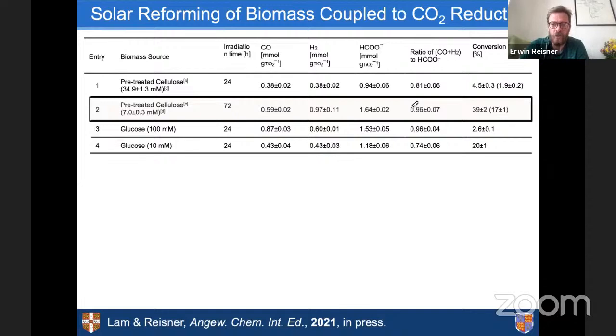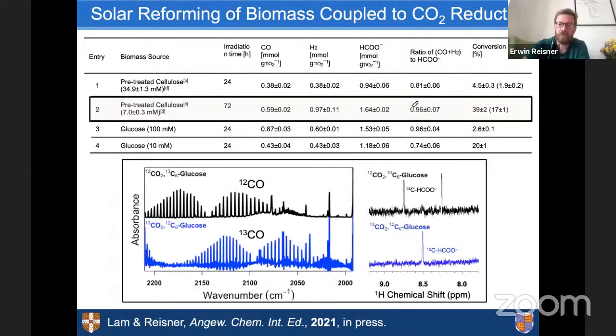But the immediate question is, with all these substrates flowing around, carbon dioxide, glucose, etc., how do you know that you form the CO from the reduction and the formate from the oxidation? And this just comes from isotopic labeling. So if you label your system with C13-labeled glucose and leave the normal C12 CO2, then you will see indeed you form C12 CO and you form the formate from the C13, and you see this nice split here. And the same is true for the opposite.